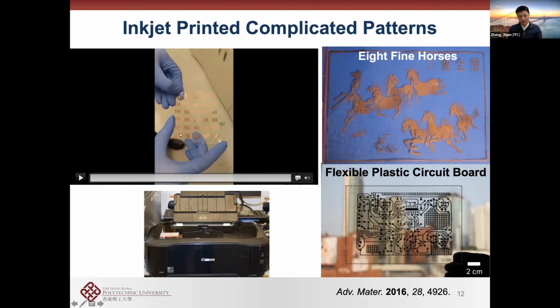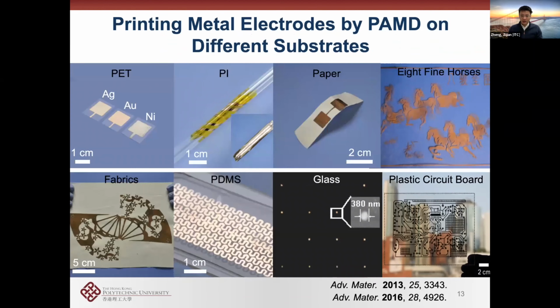So what you get in this specific example is roughly 70 nanometer thick copper. And this is very shiny copper. You know, the copper is metallic, very conductive, very smooth, and very continuous. And it's very flexible. Of course, you can ask the computer to print out different, more complicated structures on demand. So this is really nice.